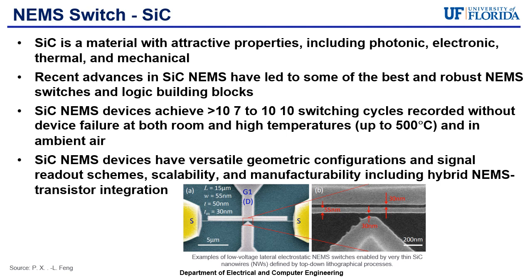They have recorded over 10^7 to 10^10 switching cycles, demonstrating reliability and endurance at room temperature and high temperatures up to 500 degrees Celsius. These devices also exhibit resilience in ambient air, offering versatility for real-world applications.